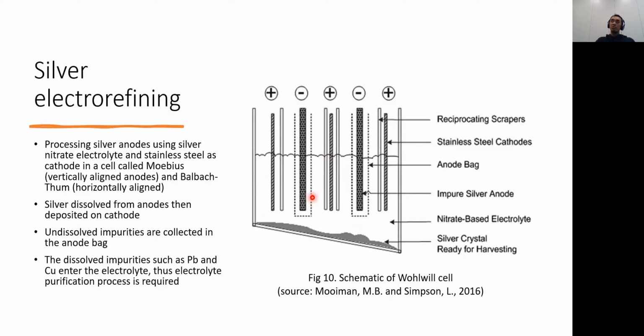So AgNO3, silver nitrate electrolyte with some kind of free acid content here. And the second difference is that the material that accumulates at the bottom is not anode slimes, but it's the final product. So this is the silver crystals.